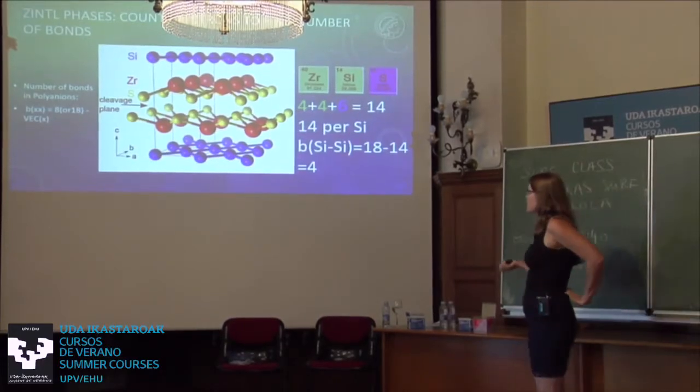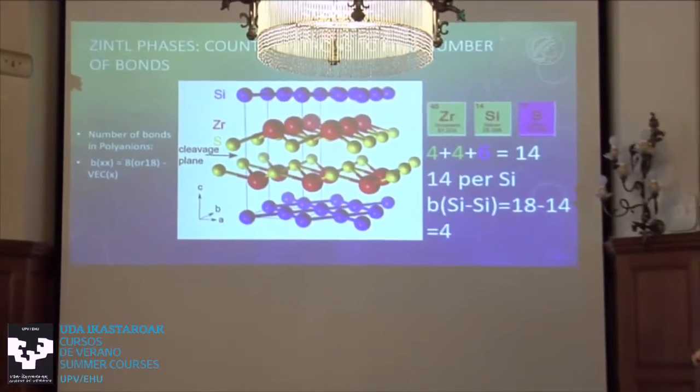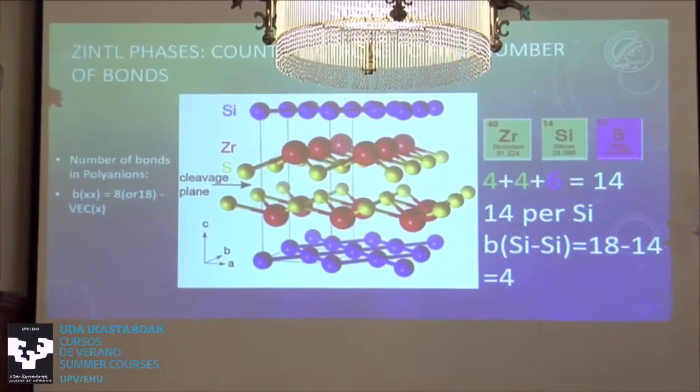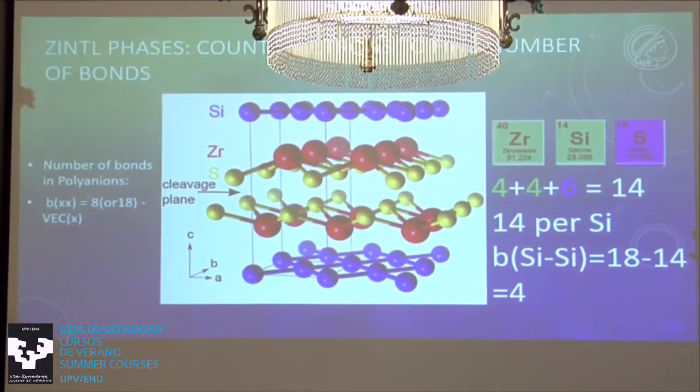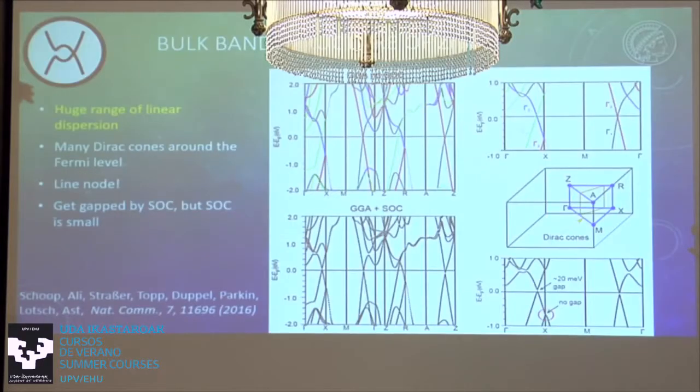And then I already mentioned this before, this is a charge balance material if you take into account the Zintl concept and the bonding, so it could be a perfect 3D Dirac semimetal just by chemical reasons. So I went ahead and did the DFT and looked at the band structure, and I found not only does it have Dirac crossings, it also has a very, very large energy dispersion. So that's the last point I wanted to improve from 3D Dirac semimetals, and it's also given here.